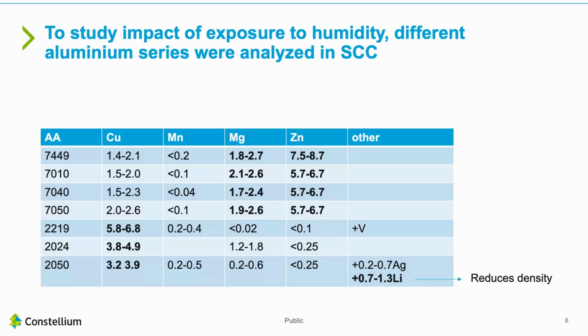We have considered incumbent 2024 for fuselage application in aircraft, and also 2050. That is a lithium-containing alloy. Around 1% lithium is added to the composition, and that reduces the density significantly. Between the 2050 alloy and the 7000 series, we have a decrease of density of around 4% to 5%. That could be seen as a low value, but when you want to increase the payload for the launcher, or if you want to add one passenger in the aircraft, it's important.